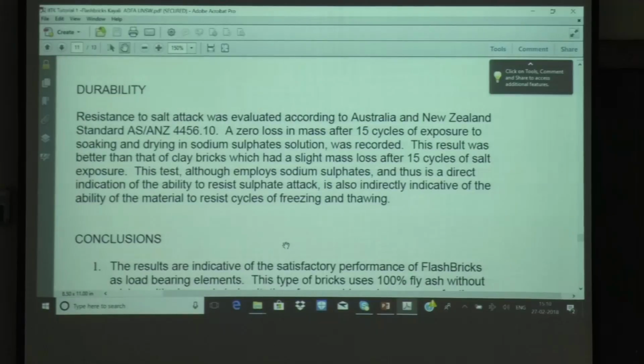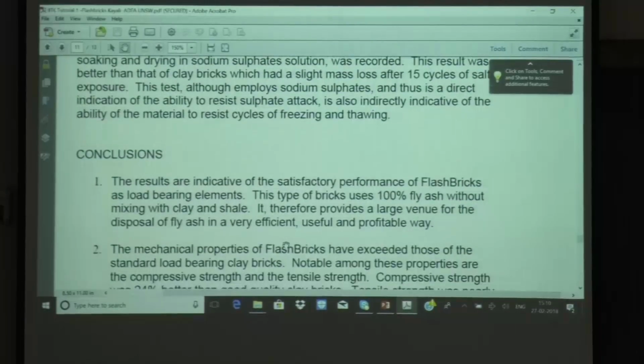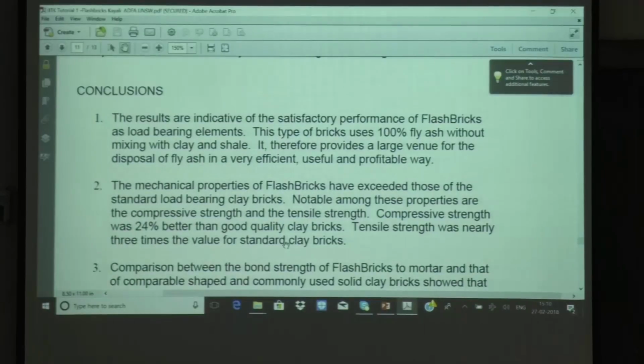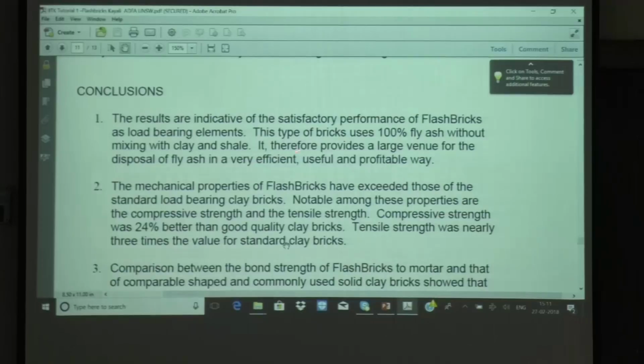And so in conclusion, this work shows that the results are indicative of the satisfactory performance of fly ash bricks as load-bearing elements. This type of brick uses 100% fly ash without mixing with clay and shale. It therefore provided a large avenue for the disposal of fly ash in a very efficient, useful, and profitable way. And you don't have to throw the fly ash onto the soil; it's in the brick. So the health problems are much less.